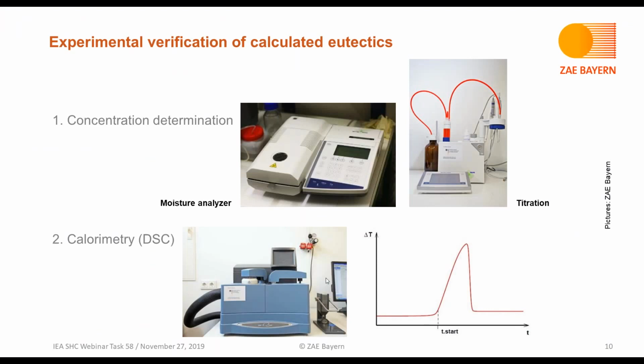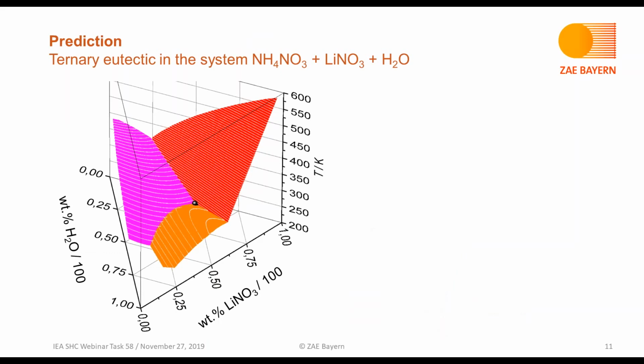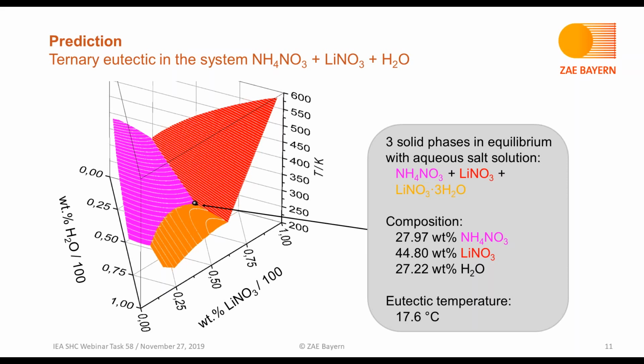The second step is to perform calorimetric measurements. Therefore, we're using a DSC, differential scanning calorimetry. To explain it in more detail, I'll give you a brief and rather simple example. Here it's the ternary system containing ammonium nitrate, lithium nitrate, and water. Shown on the left is the phase diagram, the 3 solid phases that occur here, and indicated as a black ball is the location of the ternary eutectic. In the calculation step, the information that we get is the 3 phases that are in equilibrium with the salt solution, the eutectic composition, and the eutectic temperature as indicated here.